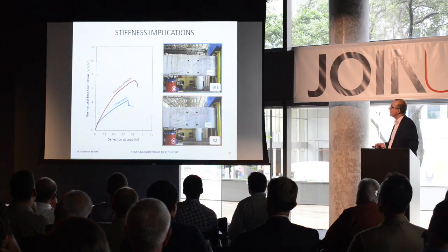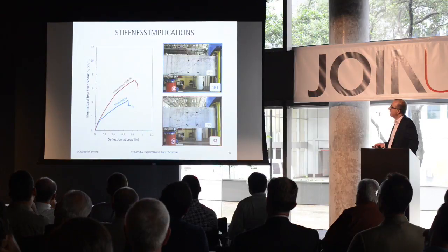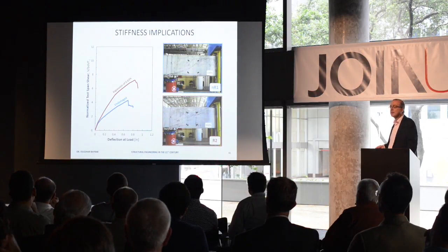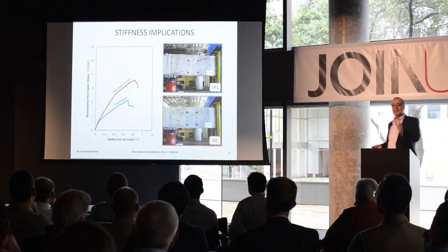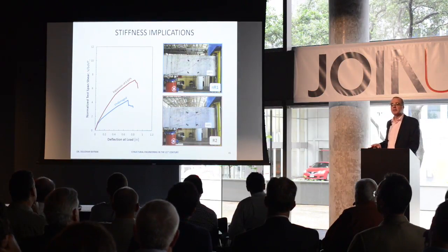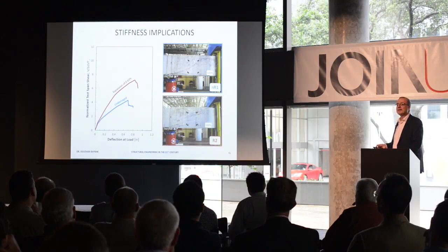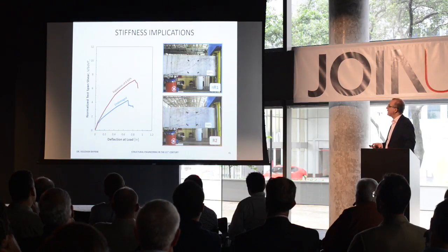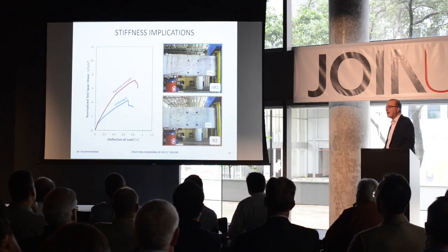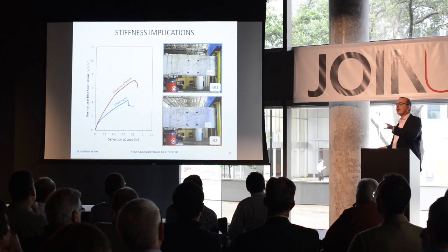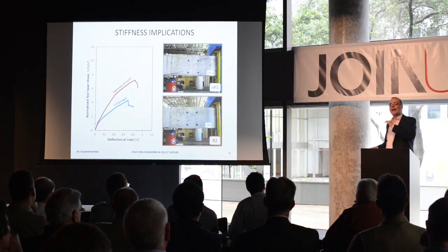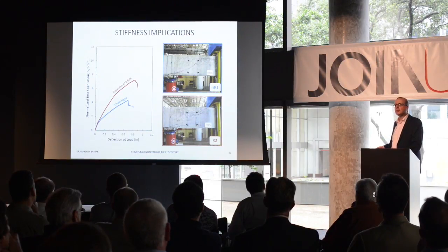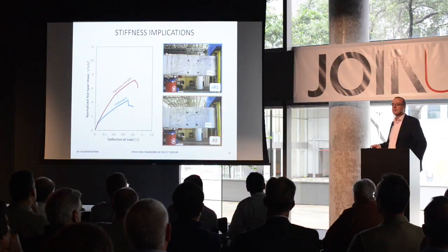So in the linear elastic range, the impact of ASR is equal to 0. Past the cracking point, it looks like the stiffness is a little better than the control specimen, and the strength appears to be significantly better. I can tell you that the graphs have not been mislabeled. You're looking at real data, and what this leads us to say, and we have said it in our TxDOT report, is that basically due to a chemical degradation mechanism called ASR and its impact on the shear strength of reinforced concrete, there is no impact.